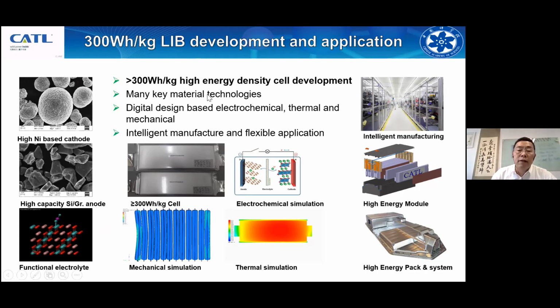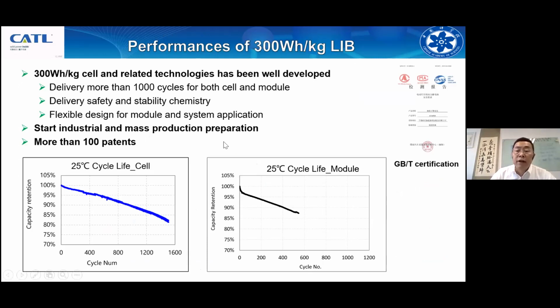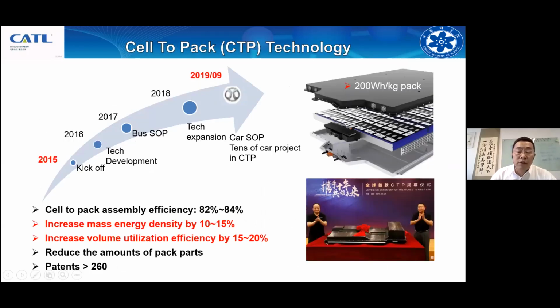For this kind of high energy density, they mainly use high nickel and also a high capacity silicon graphite combination. The key issue is to solve the volume expansion issues and also safety. And here is the cycle life at 25 degrees C. They also developed a very interesting packing technology, so-called C2P, cell to pack, with very high packaging efficiency. From cell to pack, it gets 82 to 84%. This is very encouraging and supports the car for long driving distance in limited volume, and it is already used in European cars also.